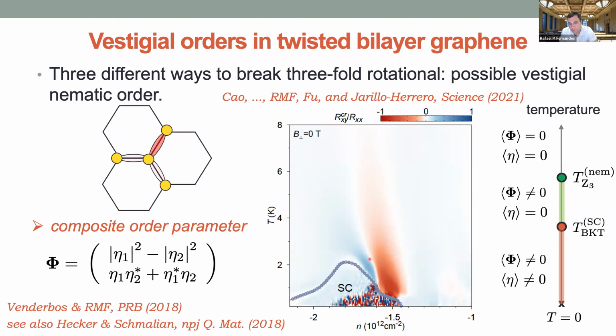Is there evidence for that? If you look at this resistivity anisotropy plot, RxY here is really a measure of the resistivity anisotropy of nematic order. There's a huge contribution from the normal state, but near the superconducting dome, there does seem to be some potential for a vestigial nematic phase.